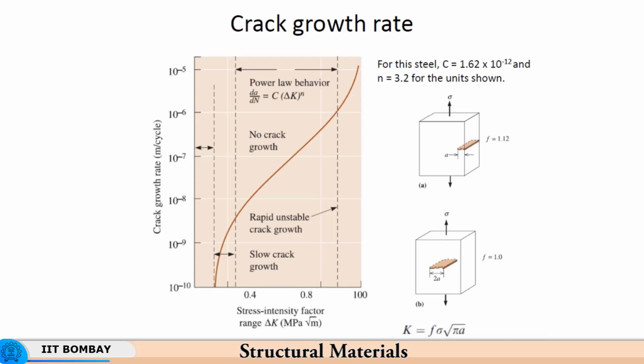Now, when you have the stress intensity factor, this stress intensity factor is basically intensification of the stress due to presence of a discontinuity. So, sigma m by sigma naught. Sigma naught is the average stress based on the entire cross sectional area being assumed to take equal amount of load, or the stress distribution being constant over the entire cross section. Sigma m is the actual stress felt at a discontinuity. So, you have either a step or an internal flaw, or at the edge of the flaw you have a very sharp radius. There you will find the stress is not equal to the average stress, it is far higher than the average stress. That is what we call the stress intensification, right.